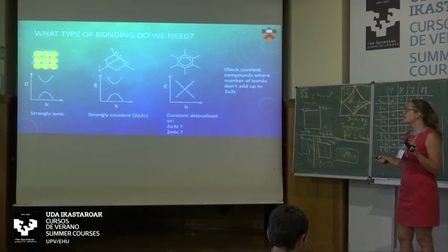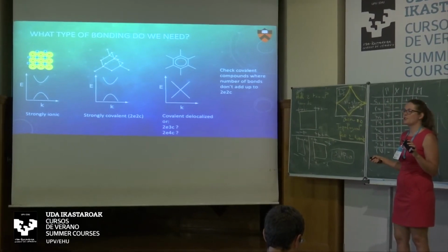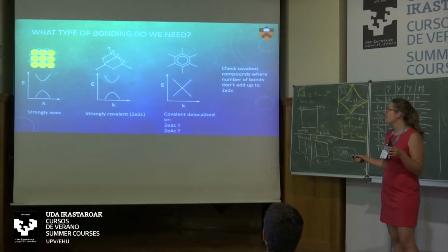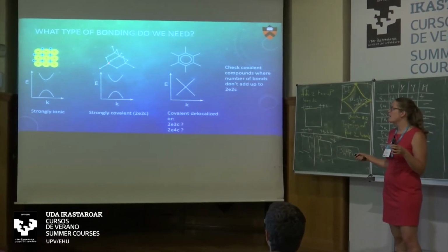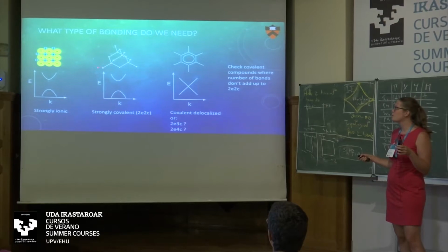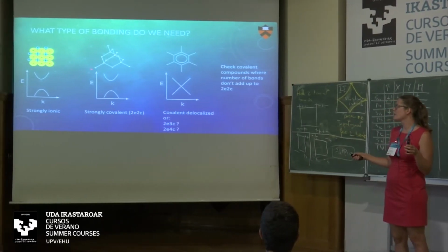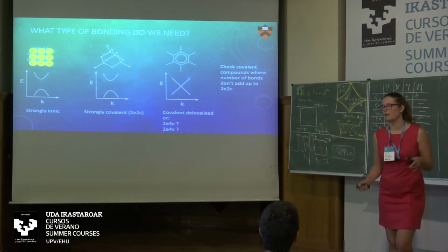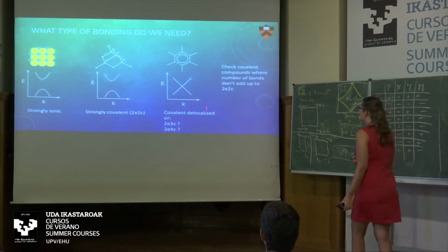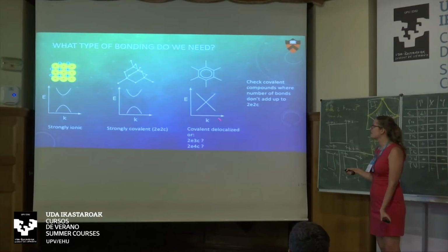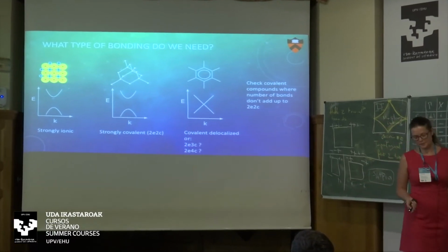And this is because here our electron count matches. In silicon or calcium silicide, which I had, the electrons match in this way that each of the bonds has just 2 electrons between 2 atoms. This is called a 2-electron, 2-center bond. So we have 2 centers and 2 electrons in between. Then it's fully charge balanced, likely to be trivial. And then we have this third kind of bonding like we have in graphene, these delocalized ones, and we get the inversion and the crossing.